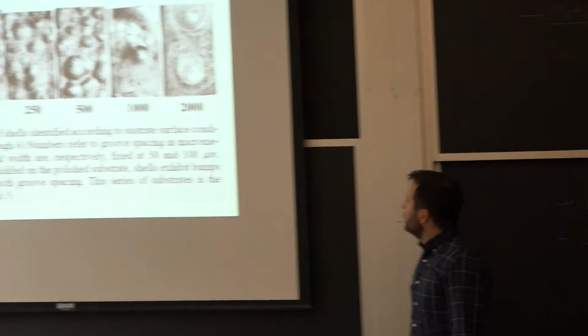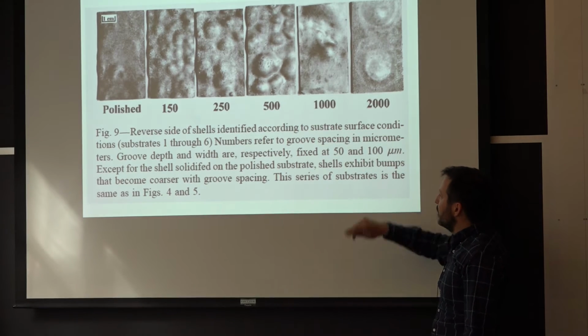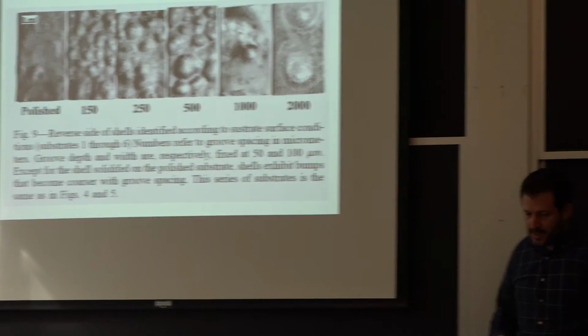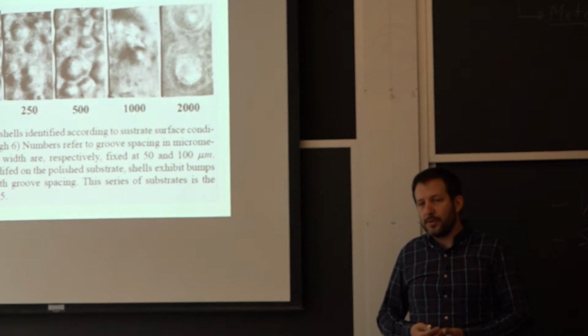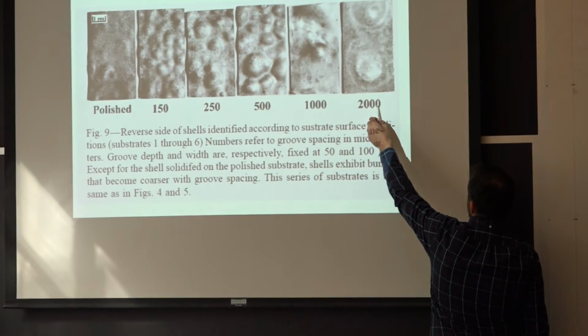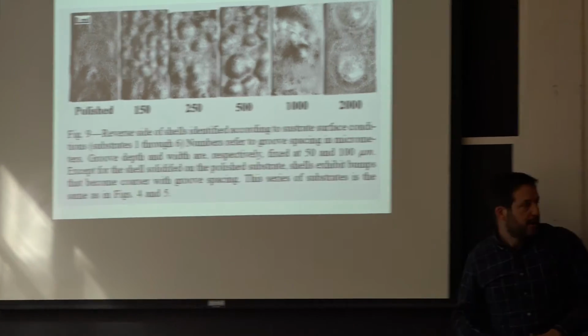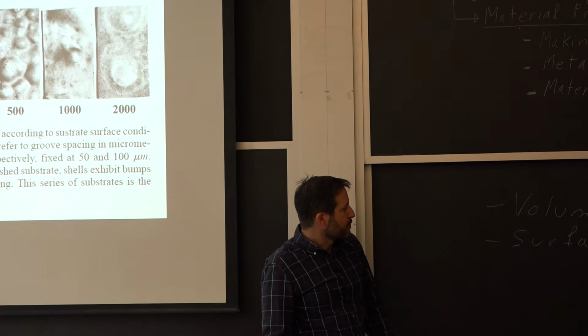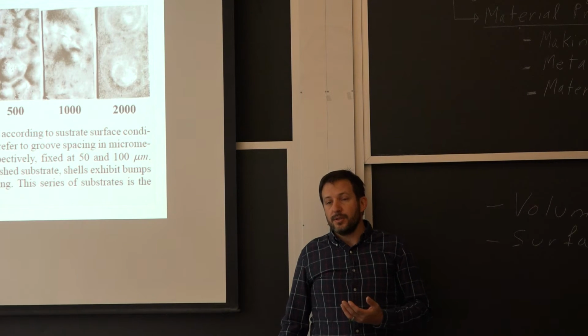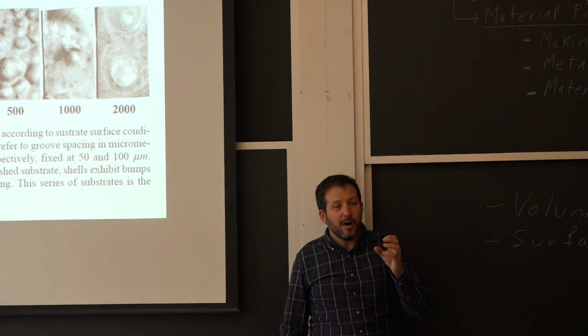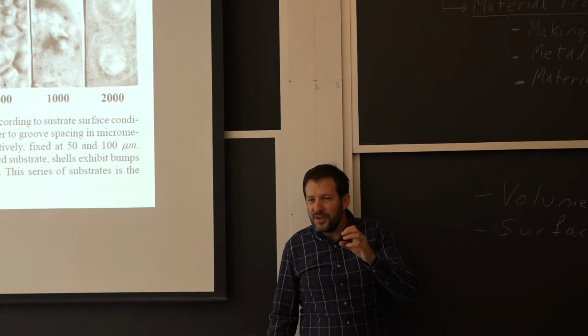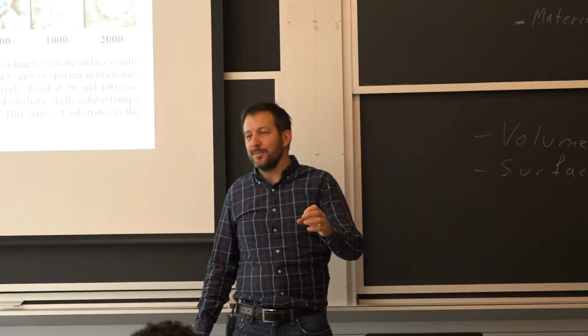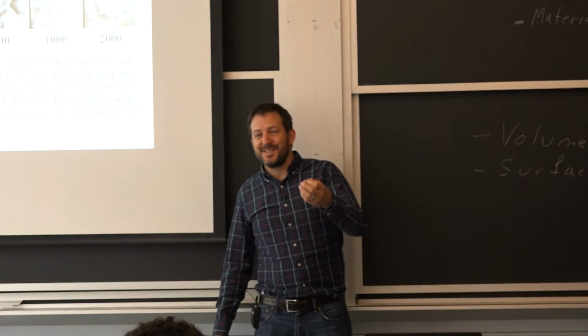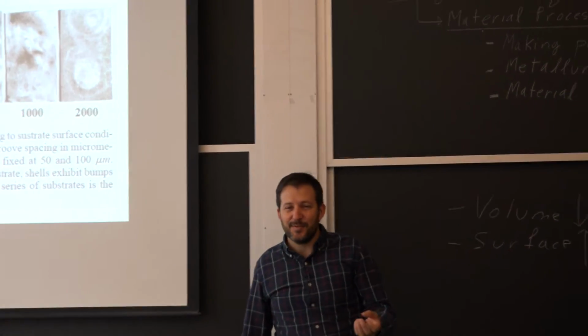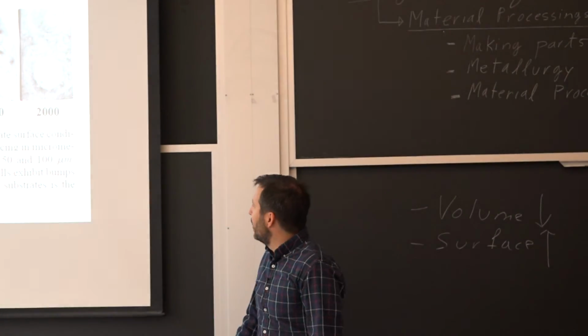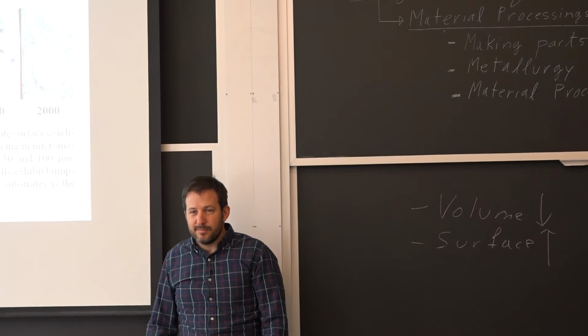So what happened? So these numbers here are the level of refinement of the sandpaper used to prepare the surface. When it's a very high number, it's a high number of particles per square inch. So that means it's a very, very fine polish. With a very fine polish, it was hard to have nucleation sites. So this one spot that I didn't do perfectly, or it was perfect, but it was still the only place that the first nuclei could start from, led to these 2 big bumps on the surface.